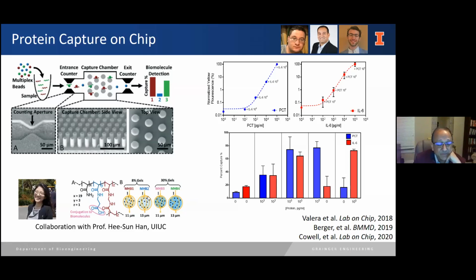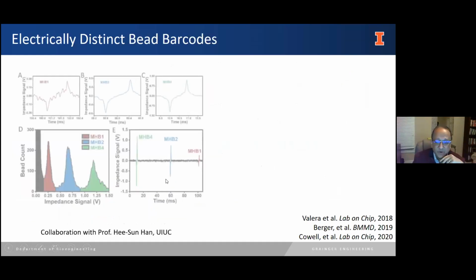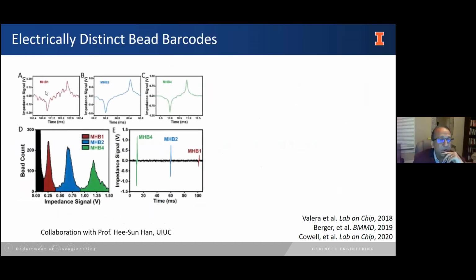She actually did that by working with our students. Her student, Michael Cole, and our students worked together to introduce magnetic particles within these polymeric beads. By changing the size slightly and by changing the composition of the gels, we can get a different electrical signature. We published that last year, where MHB1, 2, and 3 are 3 different beads. Here you can see that we can get a distinct signature from 3 different beads that are close to the same size.